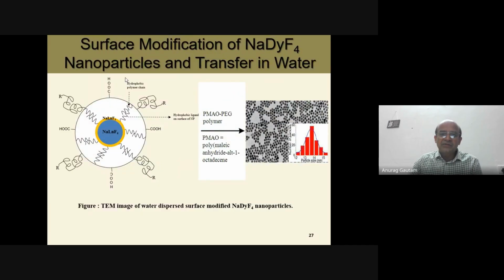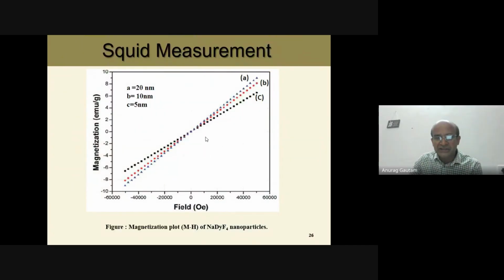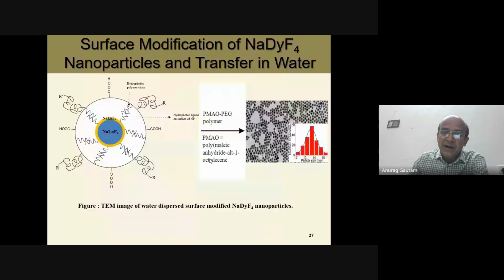And this is how we have to functionalize, because they have oleate on the surface, right? Oleate is hydrophobic in nature, so we have to make it hydrophilic. And then we also measure the size of the particle in water, because ultimately they have to go in PBS buffer solution, or water, or blood pool. So they have to be dispersible there. So their surface is modified with a hydrophilic polymer on top of the surface. Initially PMAO-PEG was there, then we coated with the hydrophilic polymer on the surface.